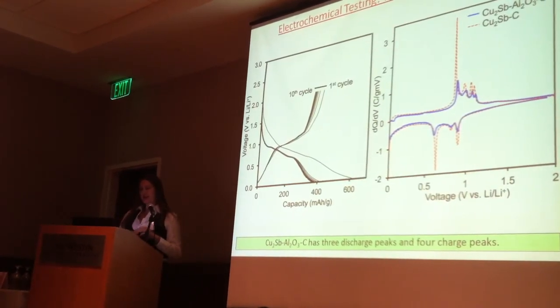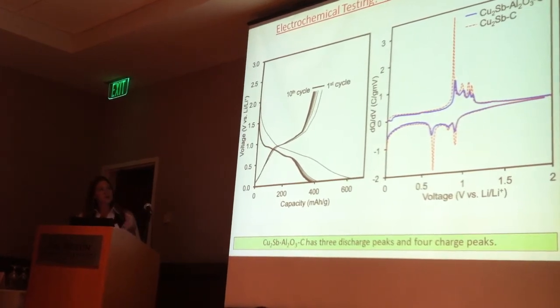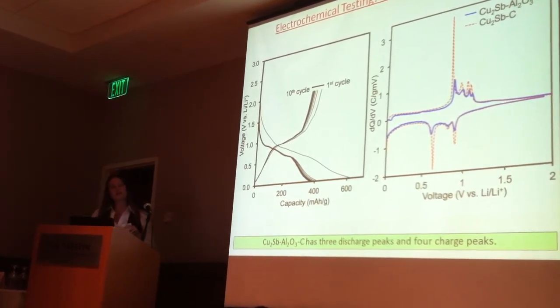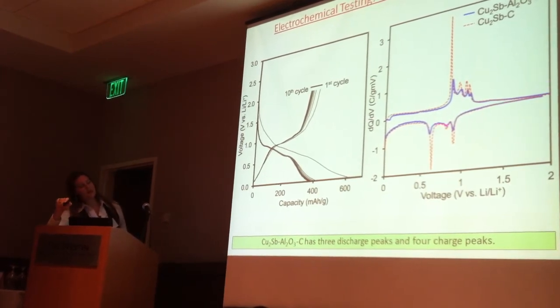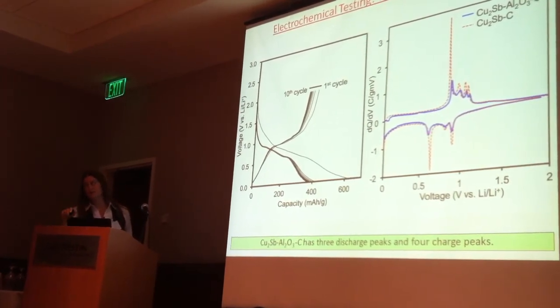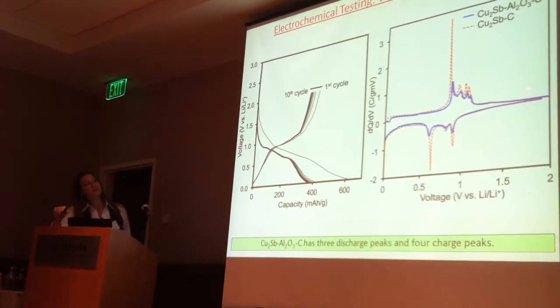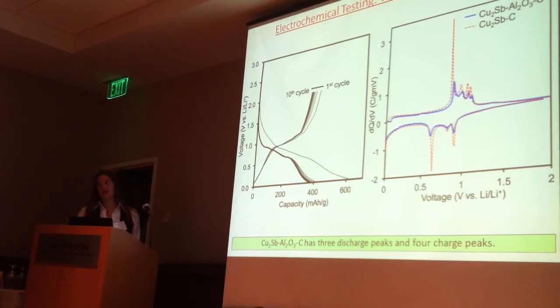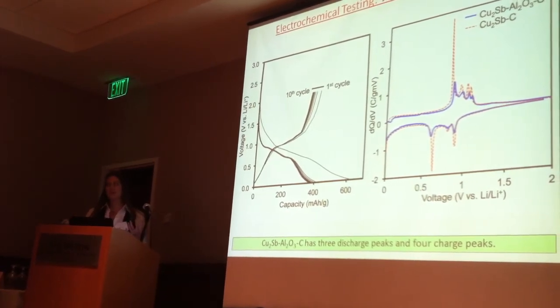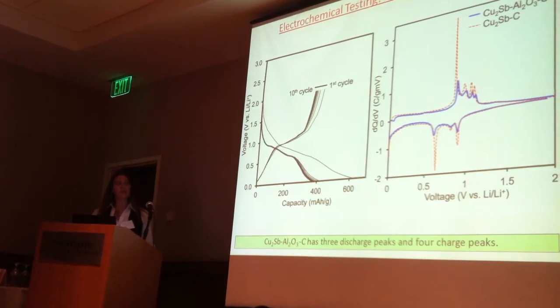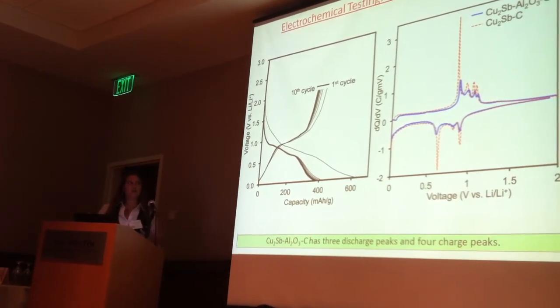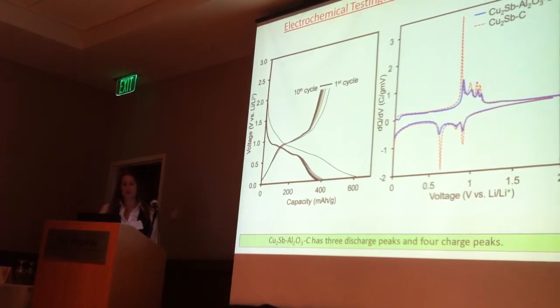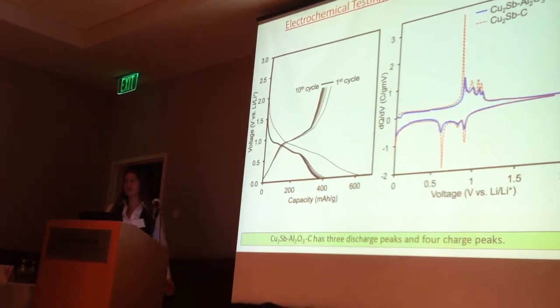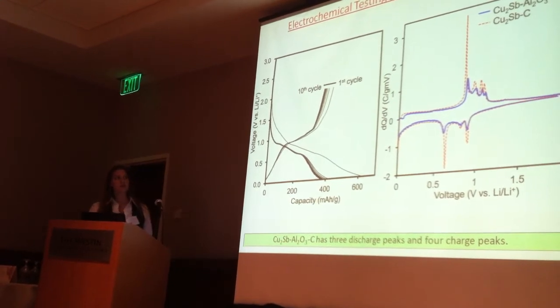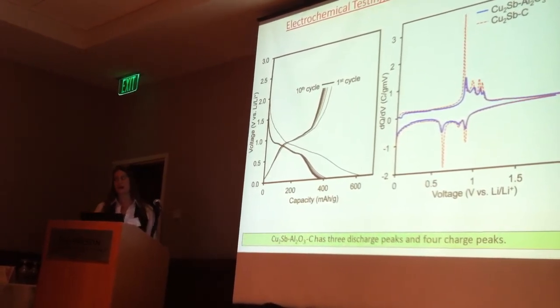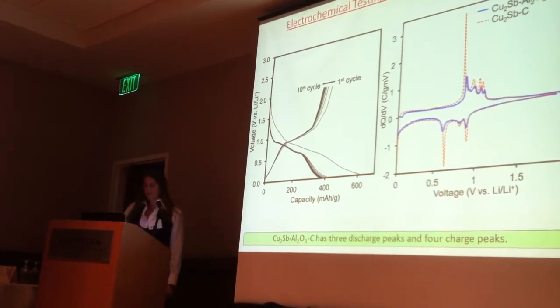We also looked at the voltage profile and the corresponding differential capacity plot, and you notice something that's a little bit strange. We have 3 peaks down here in the lithium insertion range, and we have 4 peaks in the lithium extraction range. And you might think that one of those peaks was an irreversible reaction, but if there was a significant irreversible reaction showing up in this DCP, we might expect to see a cycle performance that wasn't quite as stable. So our thinking is that there is some sort of asymmetry in the reaction mechanism for this material.